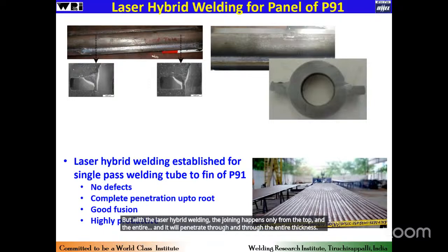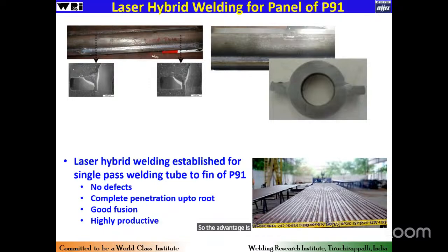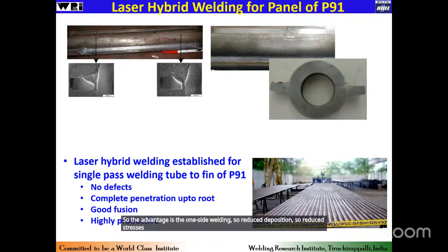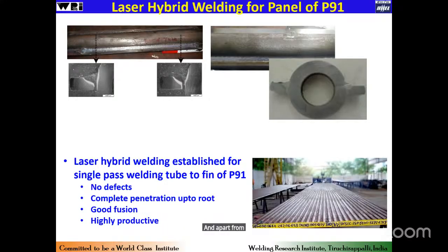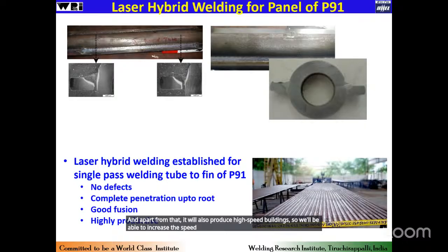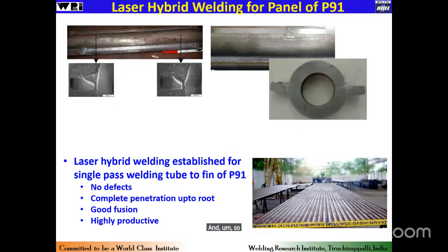So the advantage is the one side welding, so reduced deposition, so reduced stresses. That is one thing. So for this kind of restraint joints, the cracking tendency can be reduced. And apart from that, it will also produce a high speed welding. So we will be able to increase the speed at least by 3 to 4 times compared to the conventional processing, where speeds in excess of a meter per minute can be achieved. And so that will improve the productivity.